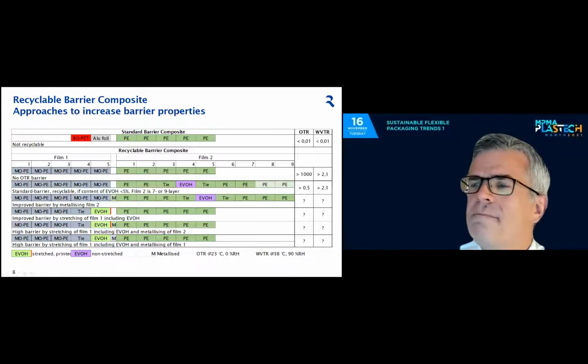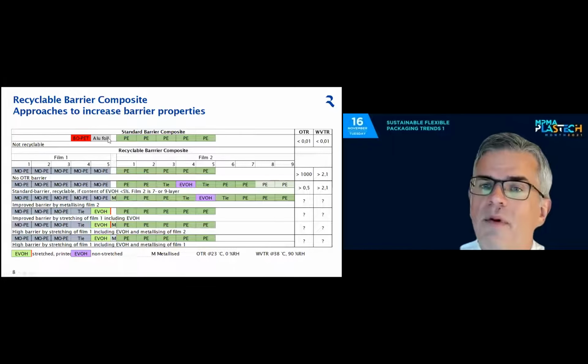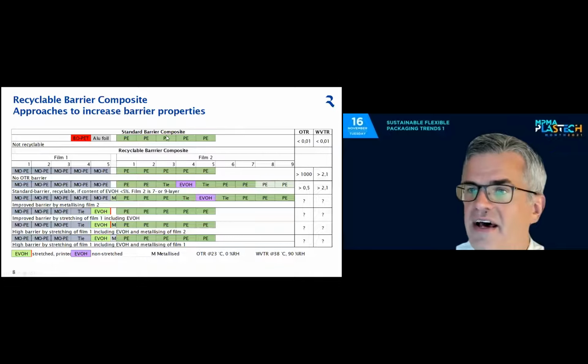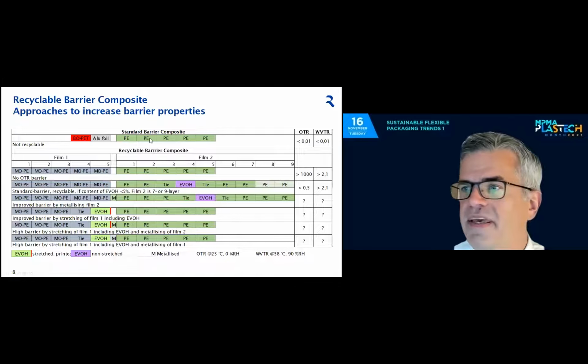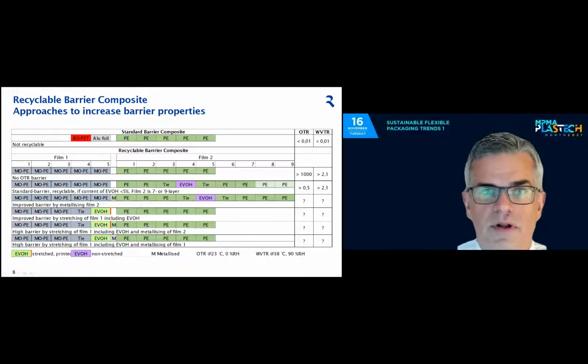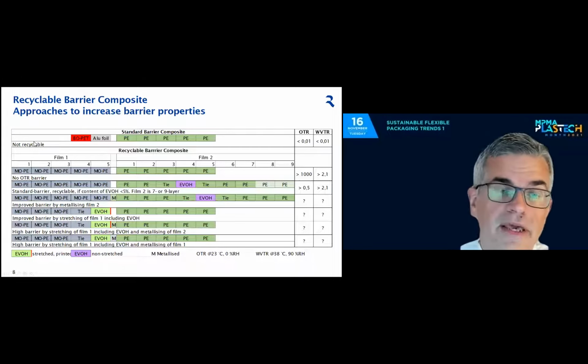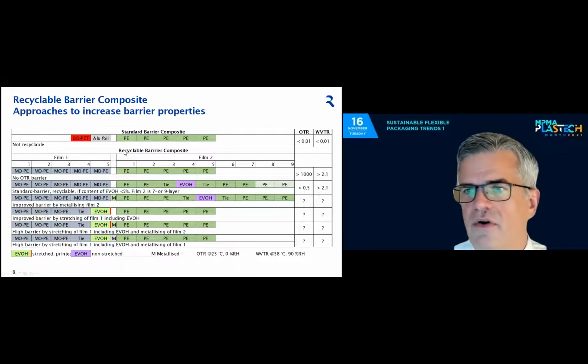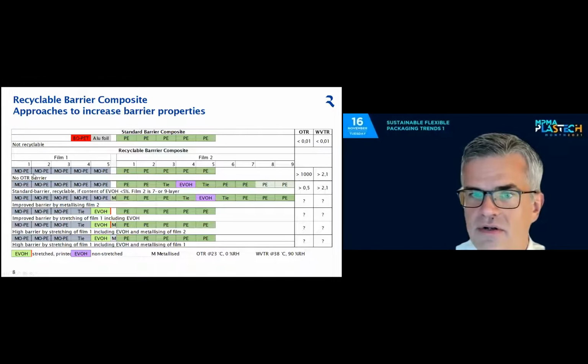At the moment, we have properties with a standard barrier composite made of bio-PET, aluminum, and a PE film, like an oxygen and water transmission rate well below 0.01. Unfortunately, not recyclable. So if we look at the standard pouch, I mentioned it in the beginning, which is made of a stretched PE film, film number 1, and a lamination film out of polyethylene.